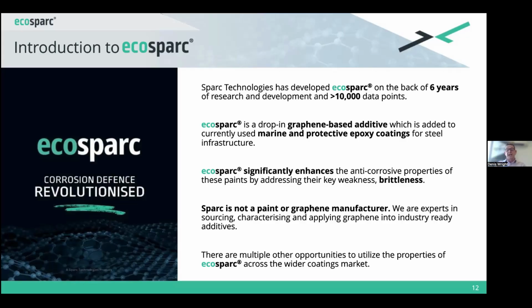The cause is it's actually supporting the polymer film or the coating film on the steel. That gives an apparent improvement in adhesion, improvement in flexibility, and improvement in crack resistance, but the upshot of that is that you get an improvement in the corrosion resistance that you see as tested by scribe creep. We're not a graphene manufacturer. We use graphene from around the world. We're agnostic is probably the word to use for that. And we look for the best graphene sources that we can get to do the jobs that are required by our customers.